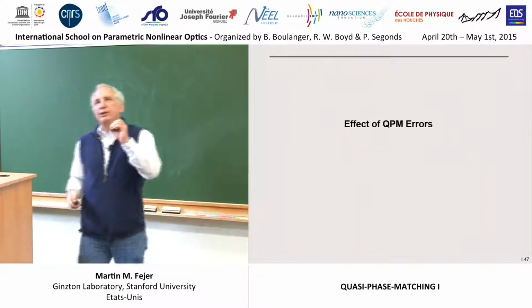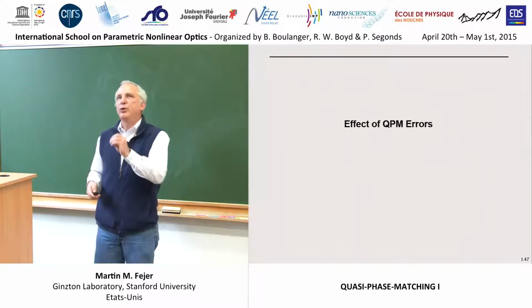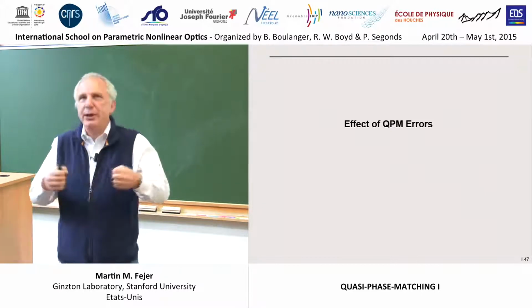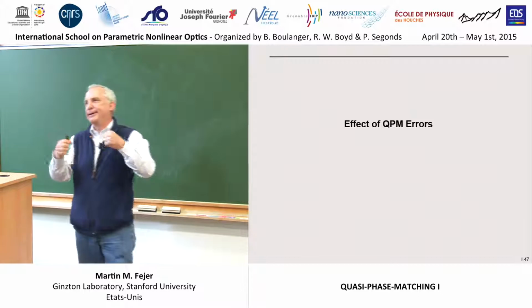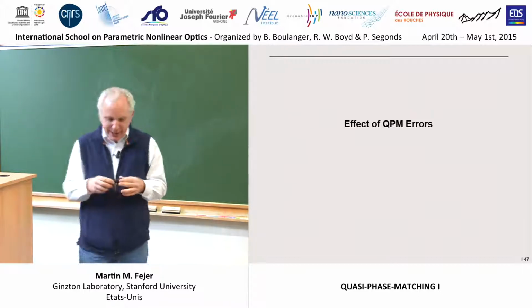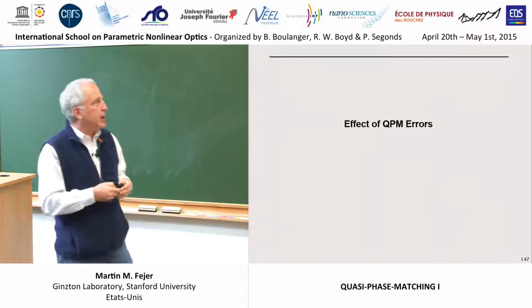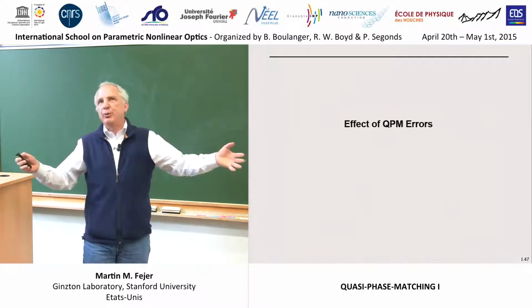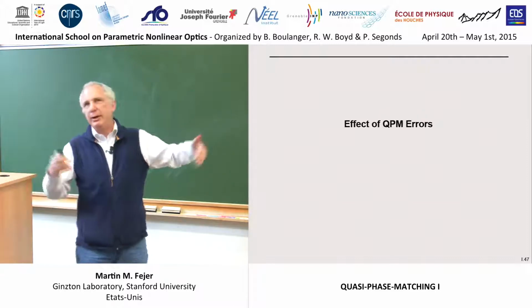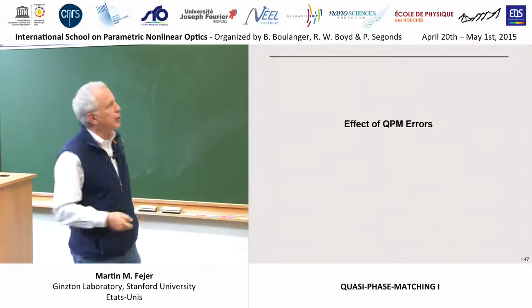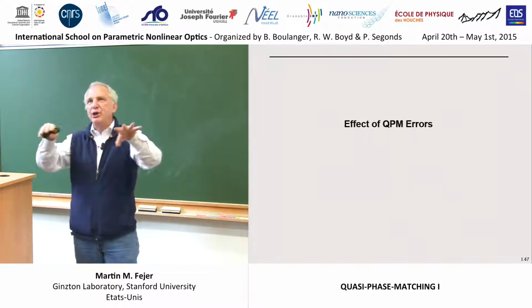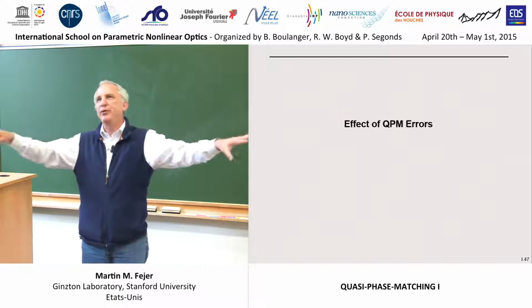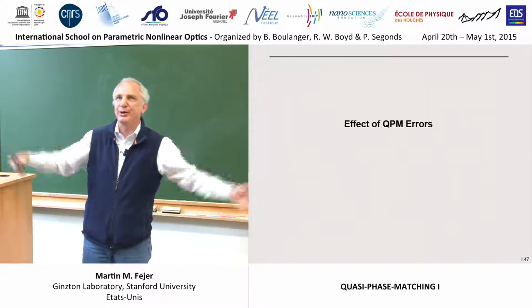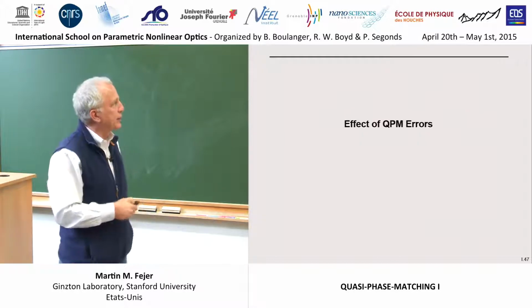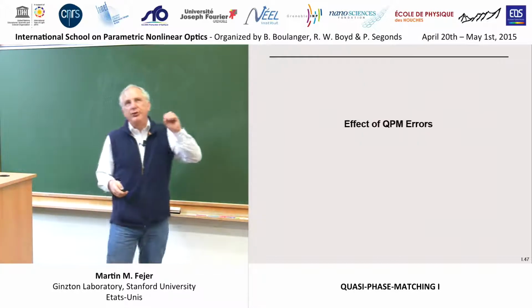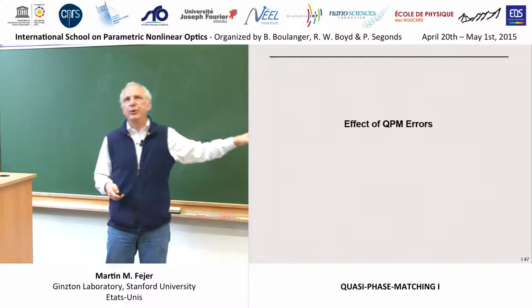Okay, so an important feature of using quasi-phase matched materials is they have one additional degree of problem that you don't get in uniformly poled materials, which is you could have a perfectly uniform crystal with perfectly uniform linear optical properties, no striations, no gradients, no anything. But if the quasi-phase matching grating you impose on it is not perfect, then you've got an imperfect nonlinear structure. And understanding the additional effects of these quasi-phase matching errors is useful for understanding why your experiment isn't working quite the way it's supposed to.